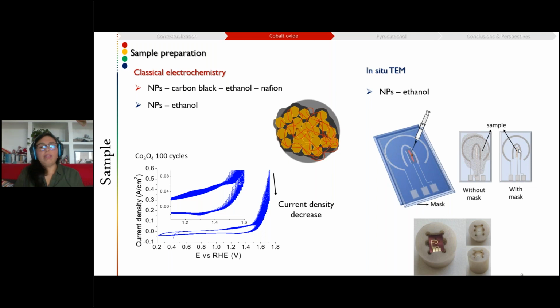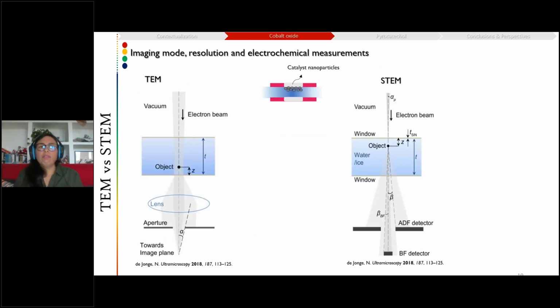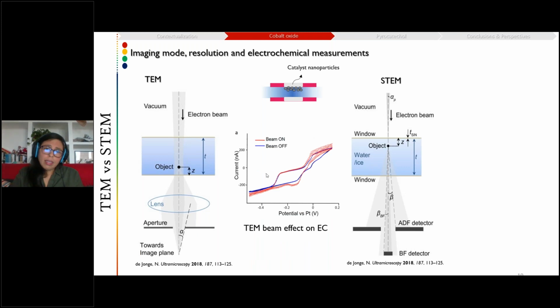After that, we thought, okay, what type of imaging mode should we use, TEM or STEM? So we tested both. Of course, both will give us different advantages and disadvantages in terms of imaging. If we use TEM, we would be able to focus more on the particles at the bottom of the chip. For STEM, more of those at the top of the chip. Besides that, if we use TEM, we see that there is a strong influence on the electrochemical behavior of our sample due to, of course, the high influx of electrons coming from the TEM mode.